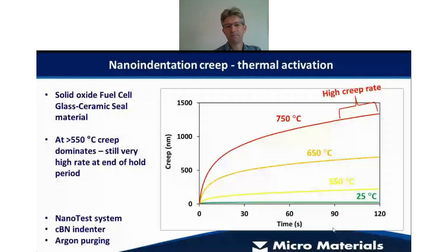This reminded me of another example. In this case, this is G18, which is a glass ceramic seal material in a solid oxide fuel cell. This material is quite creep resistant up to about 550 degrees, but above 550 degrees, it's really susceptible to high rates of creep. I illustrated that with the red curve, and you can see that high rate of creep is retained at the end of the loading period.